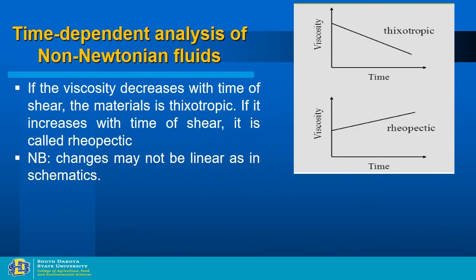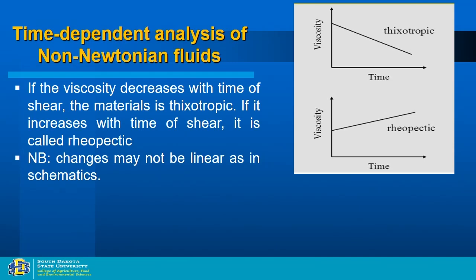When we talked about viscosity, we looked at only the time independent behavior of food materials. We have looked at the Newtonian and non-Newtonian fluid. We did not have a chance to look through the time dependent behavior of the materials. So, in time dependent behavior of the material, what we do is we measure the viscosity as a function of the time at a given shear rate. At a given shear rate, you keep measuring the stress value as a function of time. So, when you get this stress and the shear rate, then you get the viscosity. So, this is viscosity with respect to time.